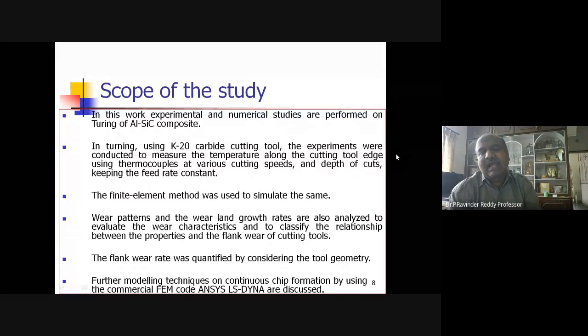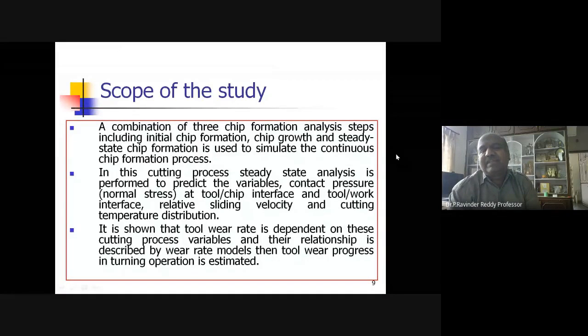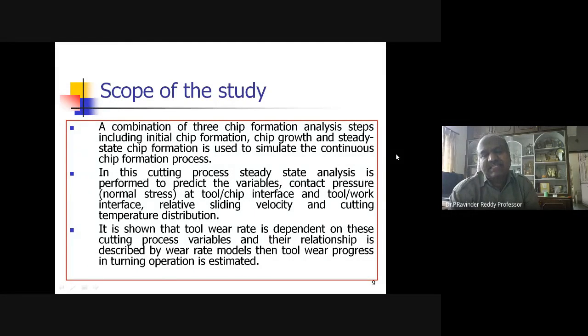Wear patterns and the wear land growth rates are also analyzed using both experimental as well as numerical simulations, to evaluate the wear characteristics and to classify the relationship between the properties. And we have evaluated the flank wear land growth on cutting tools. The flank wear rate was quantified by considering the tool geometry. Further, the modeling techniques for continuous chip formation using the commercial FEM code ANSYS LS-DYNA are also presented in the following slides. A combination of three chip formation analysis steps, including initial chip formation, chip growth, and steady state chip formation, is used to simulate the continuous chip formation process.